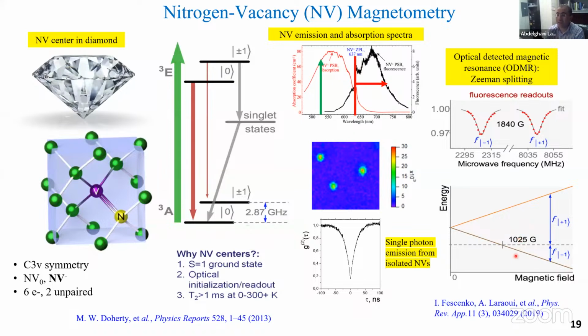measure the magnetic field, because we know this zero field splitting is 2.87 gigahertz, by measuring the frequency shift. Because you apply microwave, whenever you go to the plus/minus state, there is a chance to go to this metastable state, called the singlet. It emits less light. So by looking just at the intensity of light from here, you can know the spin state, and then you can measure the magnetic field induced by other objects when they are interacting with the NV center.